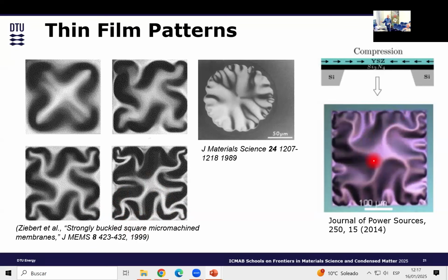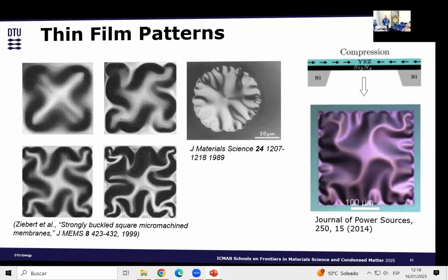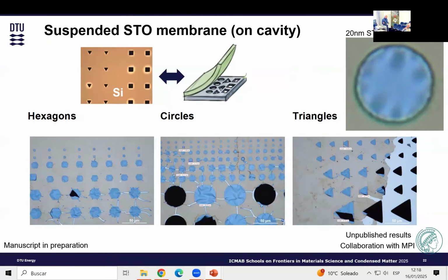And in fact, people, including ourselves, did some work many years ago on micro solid oxide fuel cells. You grow YSZ on top of silicon, then you etch the silicon below, and you can see that the material buckled, exactly the same way as a metal. So there is a relation between the buckling of the material and the film that we want to grow. And the question that we asked: what happens when we use a membrane on top of it? And that's what we did.